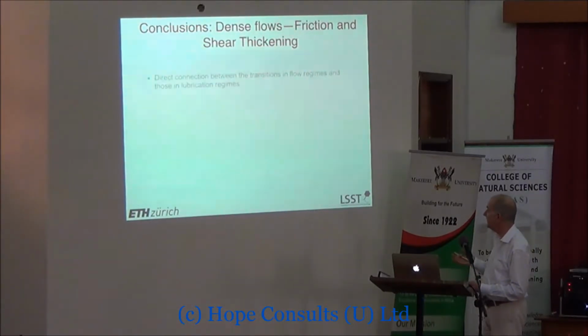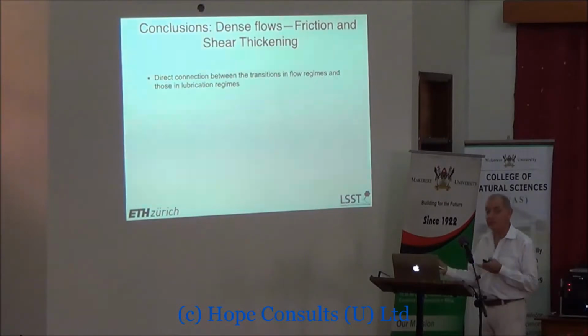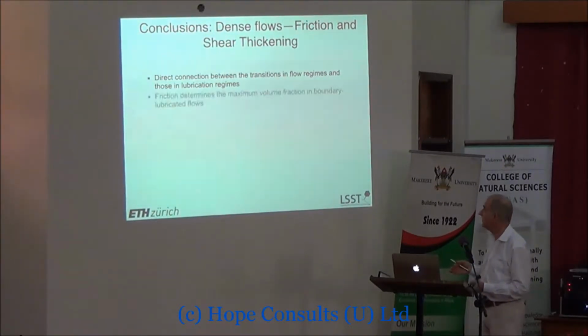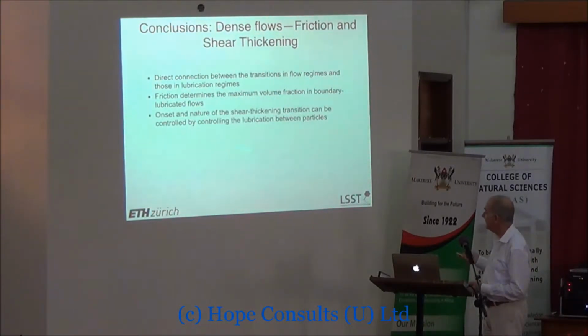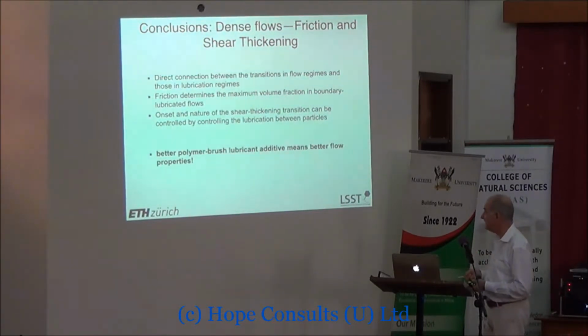So just to conclude what we could get out of these experiments and modeling, we could make a direct connection between the transitions in the flow regimes and those in lubrication regimes, so a connection between tribology and rheology. We showed that the friction determines the maximum volume fraction in boundary lubricated flows, and by controlling the lubrication, we could control the onset and nature of the shear thickening transition. And the bottom line is that with better polymer brush lubricant additives, we could make the cement flow better.